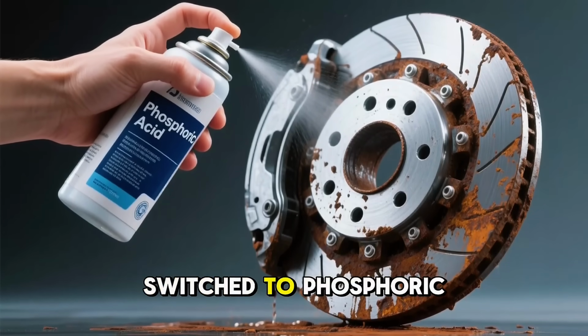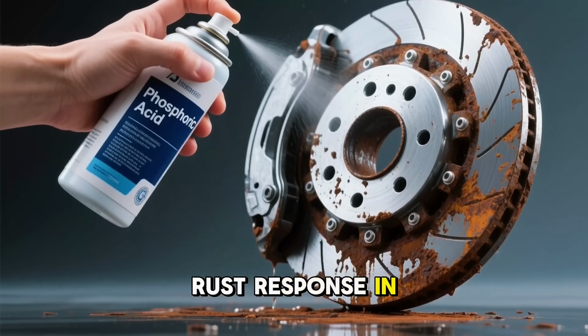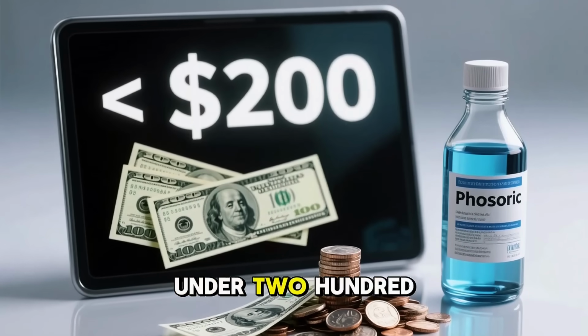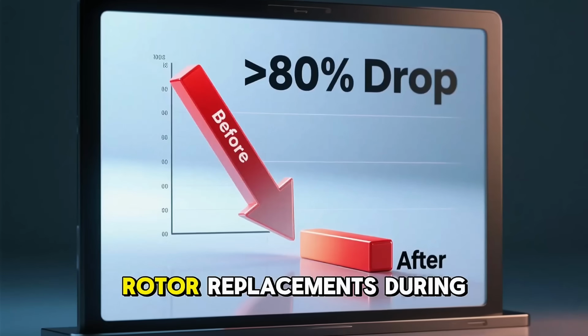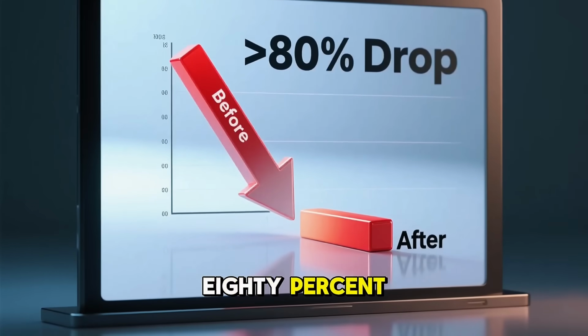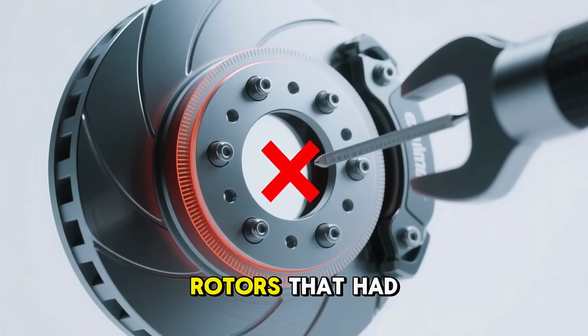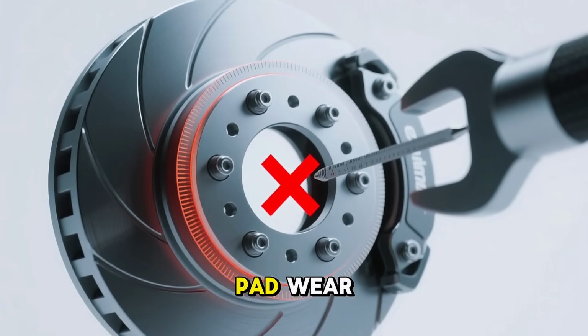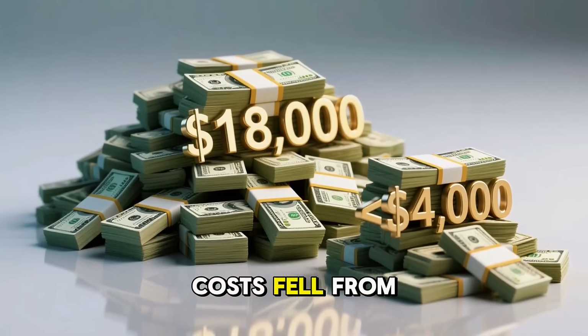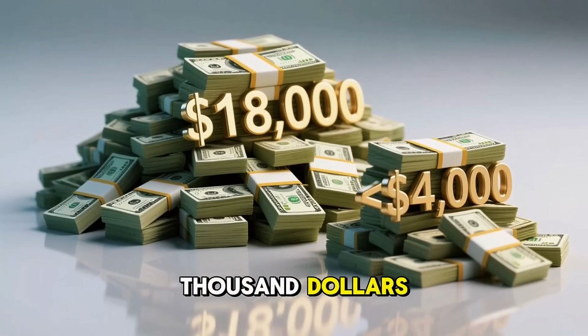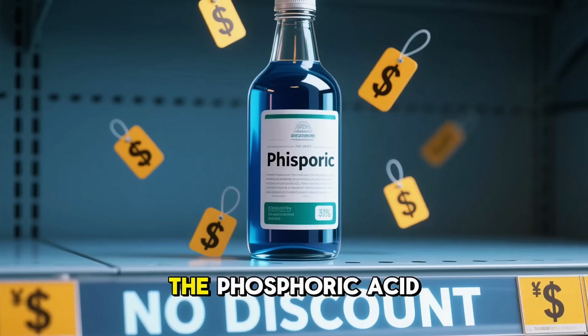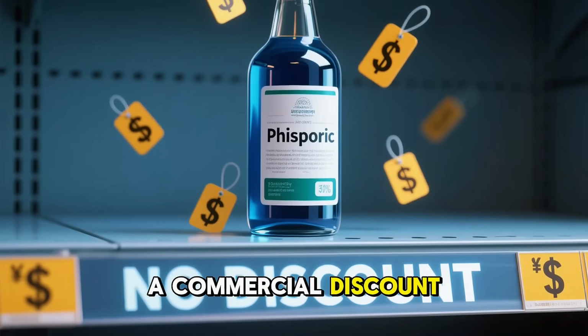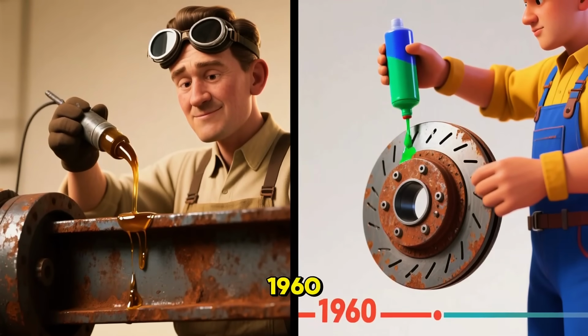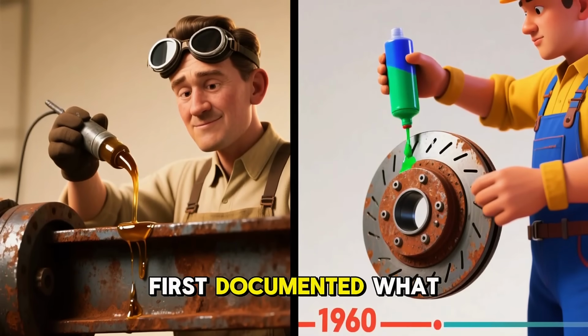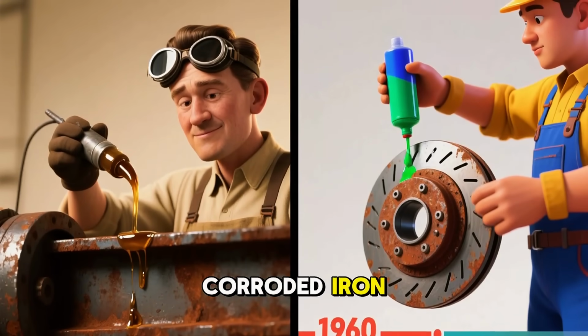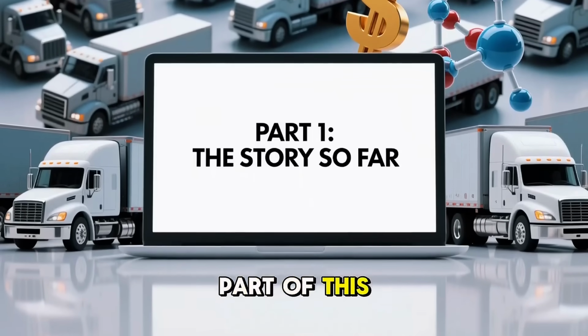The fleet manager switched to phosphoric acid treatment as the primary rust response in 2018. Over 3 years, the fleet spent under $200 on phosphoric acid. Rotor replacements during the same period dropped by over 80%, limited exclusively to rotors that had reached minimum thickness specifications from normal pad wear. Annual rotor maintenance costs fell from $18,000 to under $4,000. The chemistry does not have a fleet account. The phosphoric acid does not offer a commercial discount. It simply works the same way it worked in 1960 when industrial fabricators first documented what happens when you apply it to corroded iron.